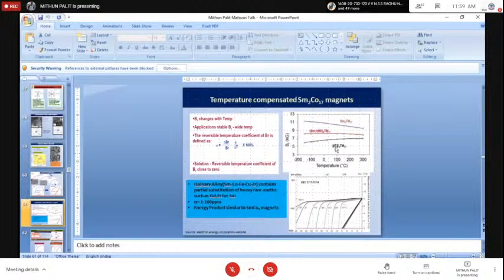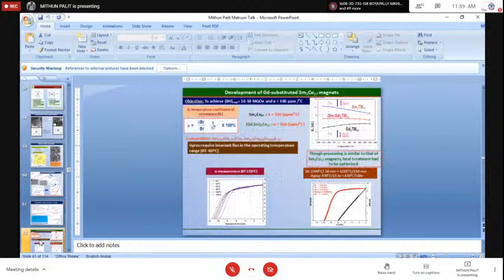However, if we add some other rare earth, in some cases it is the reverse. That means with temperature, the magnetization increases. And if we can nicely combine these two, it is possible to maintain the magnetic flux constant over a certain temperature range. So we have actually tried two different things. One is gadolinium addition with samarium. Samarium is partly replaced by gadolinium, because Gd2TM17 has a positive slope, whereas Sm2TM17 has a negative slope, and therefore in combination, if we can adjust the composition in such a way, they can be made constant over a temperature range.